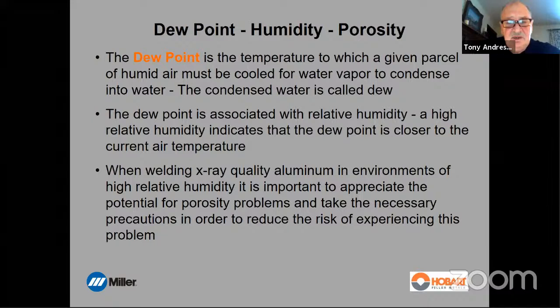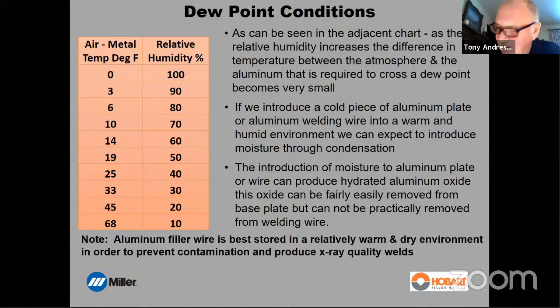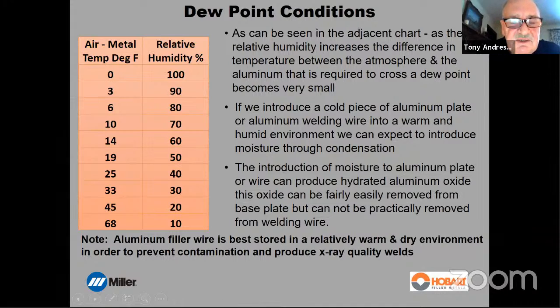Dew points, I said earlier, if you're working in humid environments, and you guys certainly do over there, then you've got to be careful about fluctuations in temperature. Small changes in temperature can cause moisture, right? To give you an idea, if we're looking at relative humidity in the 80s and 90s, very small changes in temperature between the atmosphere and the metal are necessary in order to get condensate. And you'll get moisture appearing, even if you don't see it, on the surface of your wire and on your plate. So be aware.